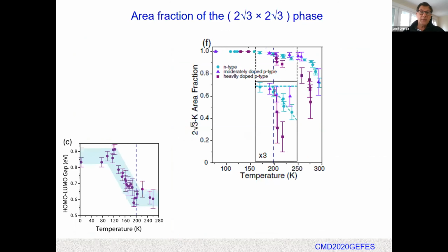So using these STM images, you can count and calculate the area fraction that is covered by the ground state, the 2√3 by 2√3 phase, for the different dopings. In this figure, you can see that up to 200 Kelvin, the whole surface is completely filled by this phase. Then starting at 200, there are some regions which are the √3 by √3 areas. And finally, there is a sharp decrease close to room temperature.